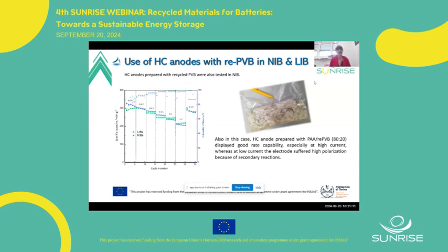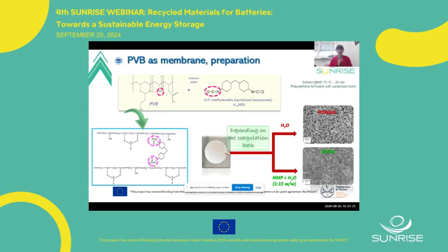However, we have some polarization during the initial cycle at low C rate, which could be due to the presence of some plasticizers. However, the results are promising for both sodium and lithium-ion batteries.